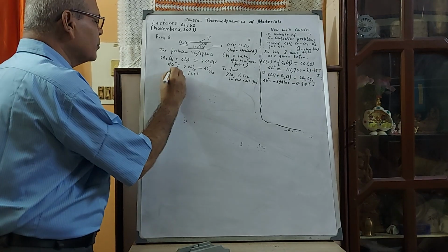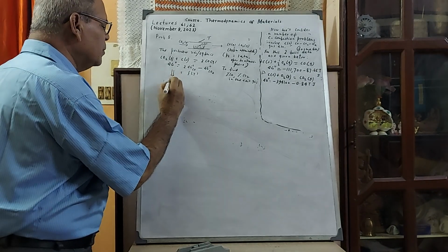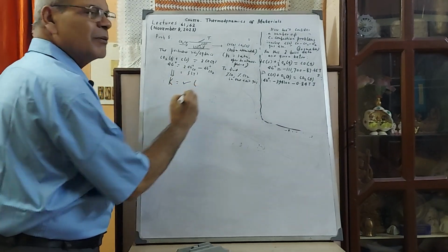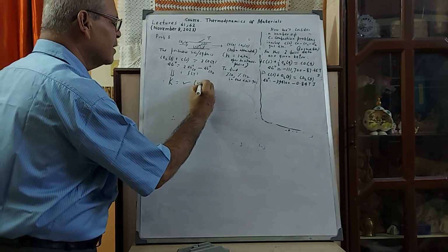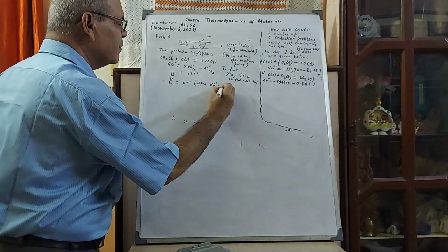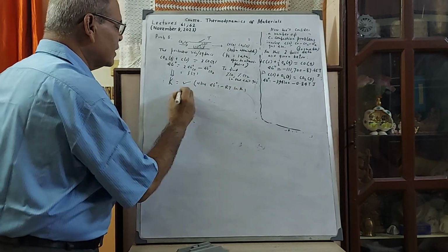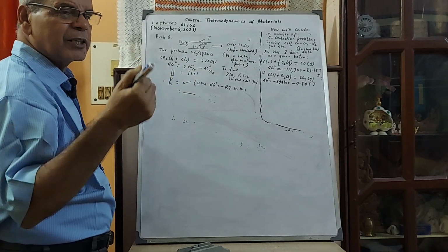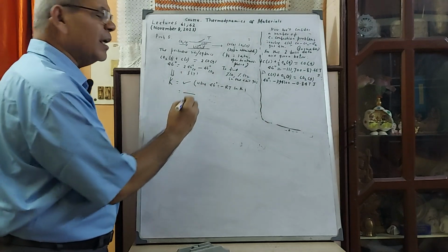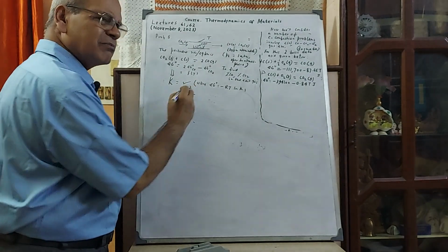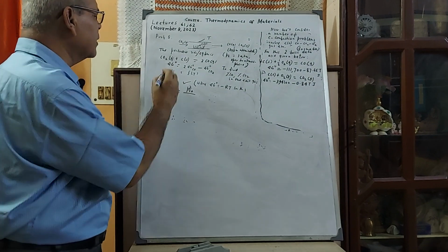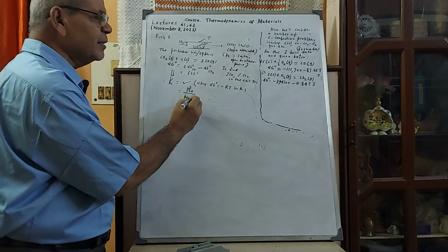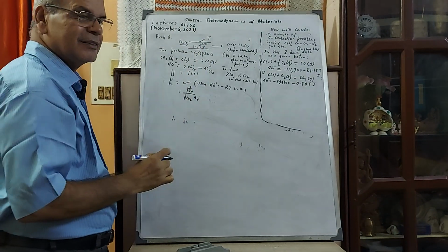Then from this you will get delta G0, and using delta G0 you will get the equilibrium constant. I'm writing it. What is K? K is known. K is what? Tell me. Hey, you are yawning. You're very tired, okay? K is PCO square divided by PCO2, times the activity of carbon. What is this value? 1, because it's solid carbon. So 1.